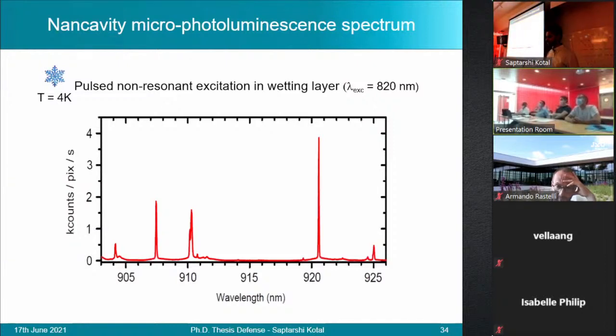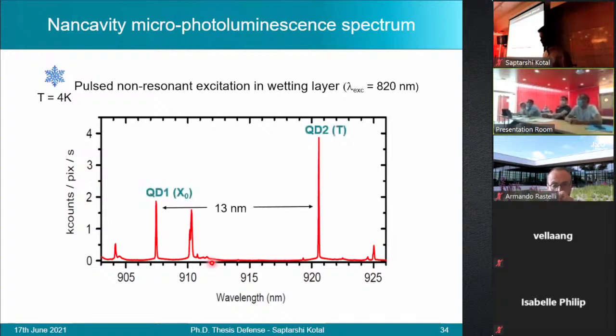Here I show you the photoluminescence spectrum of a device which is roughly 240 nanometers in diameter. Such a device typically will contain around 5 quantum dots randomly scattered across its cross-section. And the spectrum we see features isolated and sharp peaks. These peaks correspond to the recombination of excitonic complexes which are trapped in the quantum dot. In particular, we focus on the two bright lines, which we label QD1 and QD2, and they're separated by around 13 nanometers. Additional polarization dependent analyses show that QD1 corresponds to a neutral exciton, and QD2 corresponds to a charged